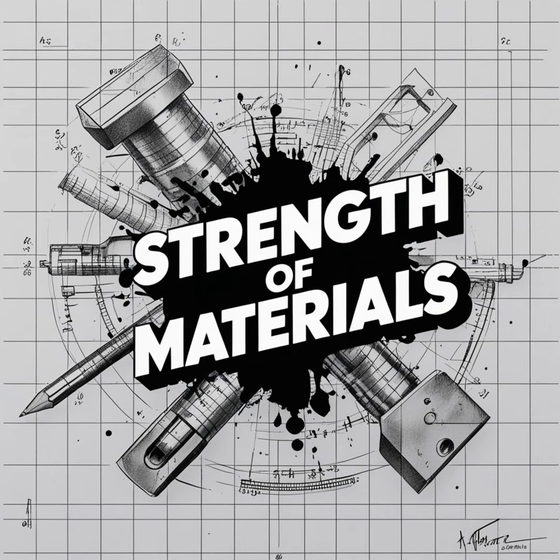But wait, do all materials have this infinite life threshold? Because if I'm building an airplane out of aluminum, does aluminum have an endurance limit? Unfortunately, no. And this is a critical distinction in aerospace. Many non-ferrous alloys, specifically aluminum and copper, do not exhibit a distinct endurance limit. Wait, they don't? No, their S-N curve just keeps sloping downward, very slowly, forever. No matter how tiny the vibration, if you cycle an aluminum wing enough times, it will eventually crack.